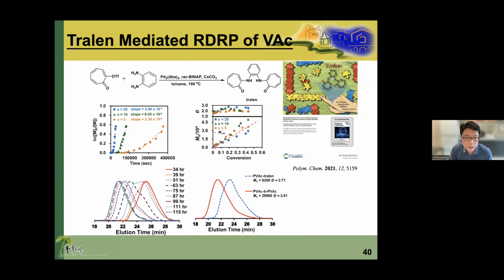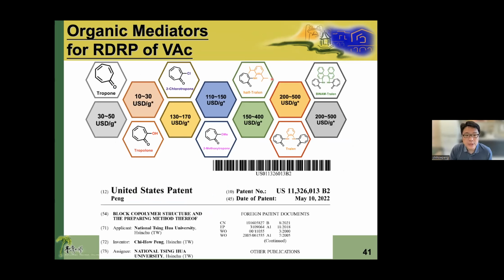It works. You can see the induction period and polymerization occur. Linear increased molecular weight with conversion, GPC moves smoothly, and we got the polymer. So we are quite excited about this, because that means we can use organic compound to mediate the vinyl acetate radical polymerization. And we further analyzed this structure. We dissected it and used the diamine and the tropone species to control the radical to test which functional group is critical to the radical polymerization. And we found actually the tropone is the more important substituent. And by optimizing the tropone species, we actually can obtain the controlled radical polymerization of vinyl acetate. And we also patented this technique and hope in the future we can industrialize this technique, because the cost and the product are all approved by some commercial companies.